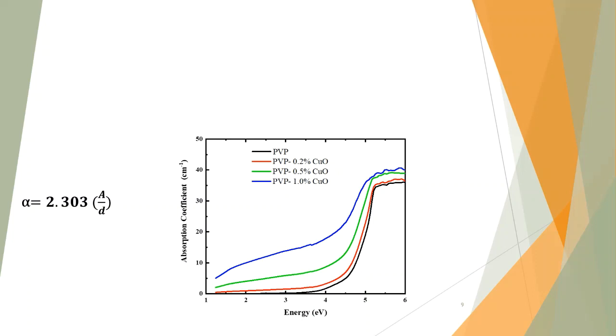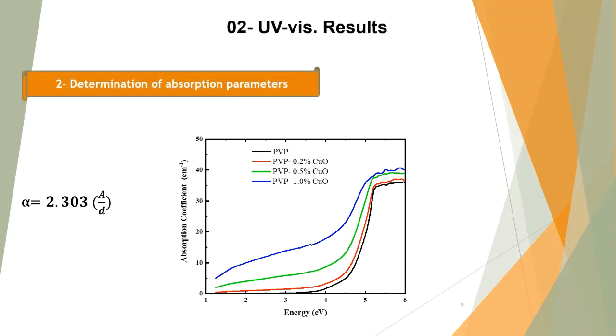As we know, the analysis of the absorption coefficient has proven to be crucial in predicting any changes in the electronic band structure of polymeric materials. Also, it is well known that investigating the fundamental absorption edge reveals important details about the optical band gap of polymers. As we can see from this figure, the absorption coefficient varies with the incident photon energy, and PVP and the nanocomposite solutions have only one absorption shoulder, which shifts to the lower energy region with increasing copper oxide concentration, and this predicted changes in the optical band gap energy.